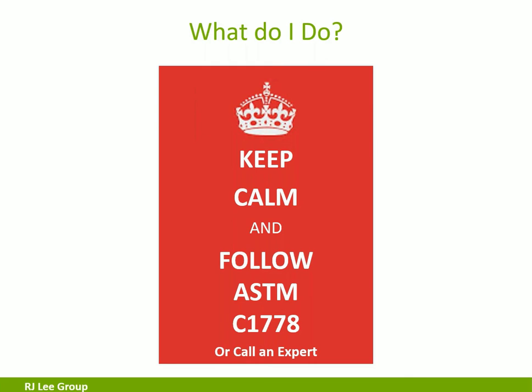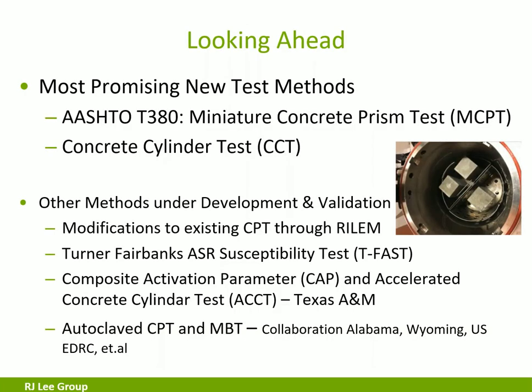Looking ahead on the ASR issue, there are some promising test methods that are being evaluated at this time. When I say they want new test methods, you want accuracy, and people just want results fast. There's a miniature concrete prism test and concrete cylinder test that is very promising. Some other methods under development and validation include modifications to the concrete prism test through RILEM. Turner Fairbank has an ASR susceptibility test they're calling T-FAST, using chemistry of aggregates to predict reactivity. The Texas A&M has a composite activation parameter and an accelerated cylinder test, and there are some autoclaves, concrete prism and miniature mortar bar tests.